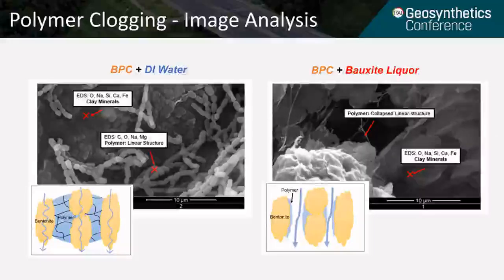But if you have a higher or stronger bauxite liquor, as we mentioned earlier, you can still find high hydraulic conductivity. The reason is this polymer swollen structure is suppressed. So here you can see the open pore spaces that is happening where no polymer is clogging this area. So that generated high hydraulic conductivity.